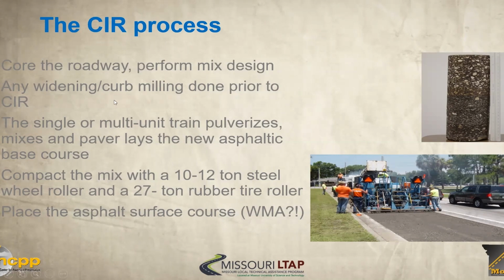And so what we're really worrying about is how deep those cracks penetrate and what's underneath maybe causing these cracks. You can use single or multi-unit trains, and they're going to pulverize, mix, and then lay the asphaltic base course. Then the process goes that we're going to compact that mix. We're going to be using a steel wheel and a rubber tire roller. That rubber tire roller is quite heavy, a 27-ton rubber tire roller, and that is because oftentimes we're compacting thicker lifts. And then warm mix asphalt could go on the surface.